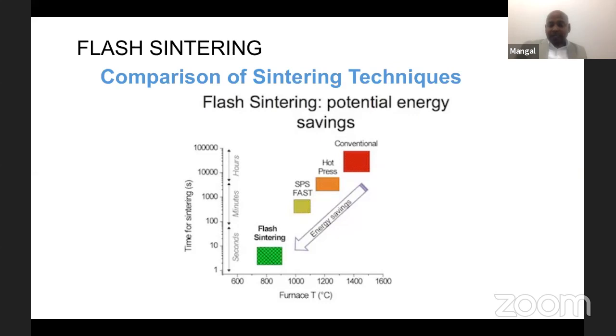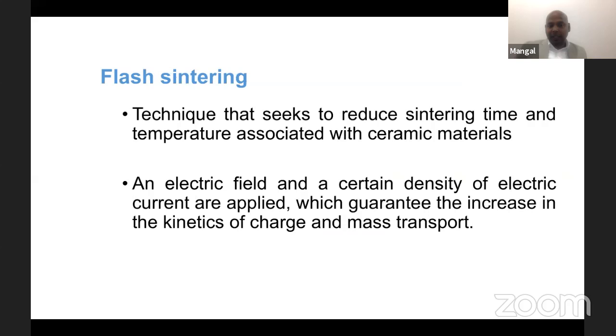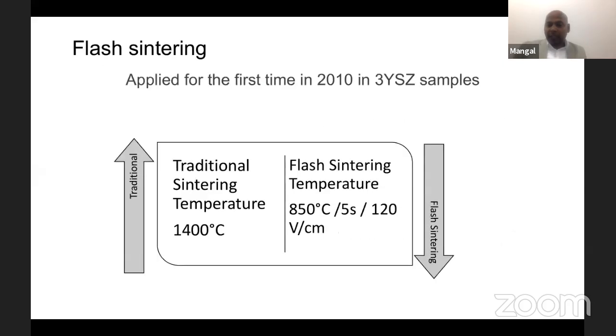So flash sintering is now under investigation, and this technique seeks to reduce the sintering time and temperature associated with ceramic materials. By applying different electric fields, you can really get good nanostructured materials. Getting nanostructured materials in a few seconds is very important, because sometimes rapid sintering can increase abnormal grain growth. But in our case, with flash sintering at 850 degrees centigrade, just 5 seconds, compare with traditional sintering at 1,400 for one day. It is 5 seconds at 850.